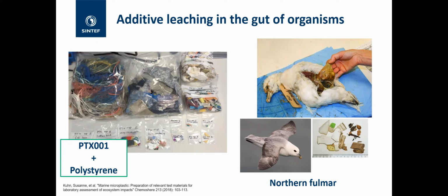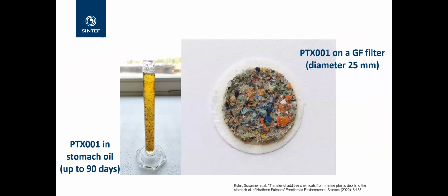seabirds. These are very well studied. They're known to collect or ingest lots of large plastic items, but they also have a mechanism in their digestive system that grinds the particles down. So I think the estimate is something like between 30 to 90 days, they will grind a lot of stuff down into small particles that they can then excrete. So we know that they have potential for a lot of exposure to chemicals.